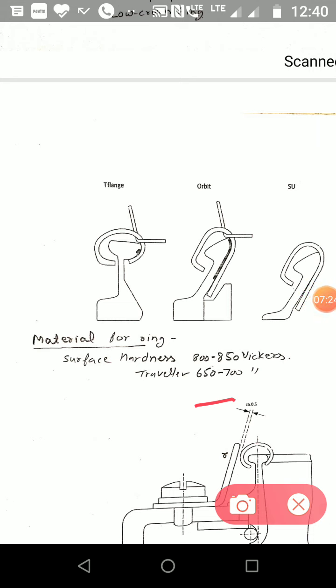A good ring should have the following features: a best quality raw material, a good but not too high surface smoothness, an even surface, exact roundness, good even surface hardness higher than that of travelers. It should have run in as well as possible, long operating lifetime, correct relationship between ring and bobbin tube diameters, horizontal disposition, and it should be exactly centered relative to the spindles.